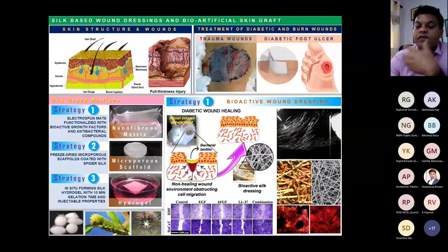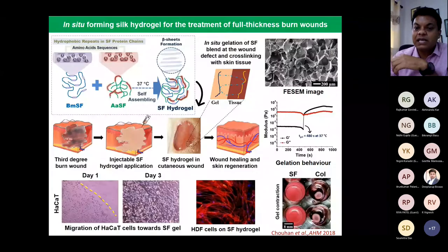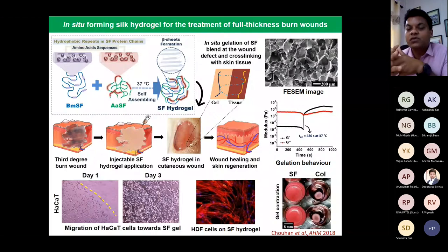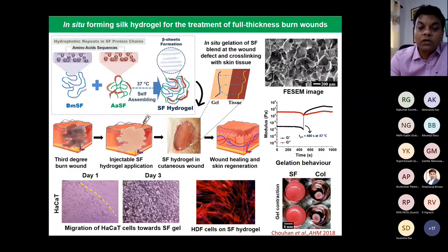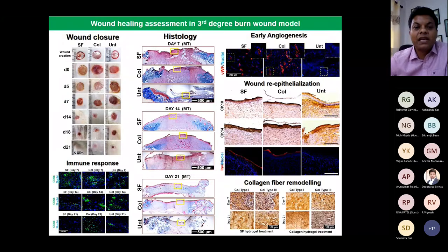So we use a lot of combinations of materials along with silk, and this is a GIST slide where it shows we form a gel using a non-cross-linking method, a green method, where additives and extracellular matrices are added. When it is applied onto the third degree burn, it allows cells to be recruited from deep down the tissue, and we can get the skin back. It has been compared with the gold standard, which is collagen, and we have found very similar results in the in vivo studies.